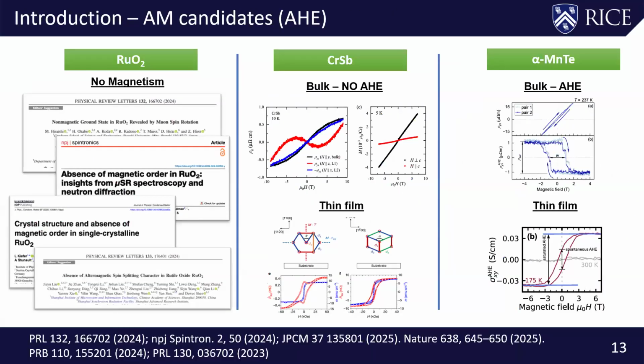So the situation in the case of ruthenium dioxide has now been clear. It's not an altermagnet. In this case, at least in bulk, there's no anomalous Hall. But in this particular compound, the anomalous Hall has been observed both in thin film as well as in bulk. In fact, many decades ago, first in transport measurements.